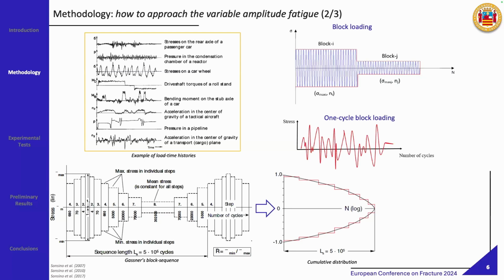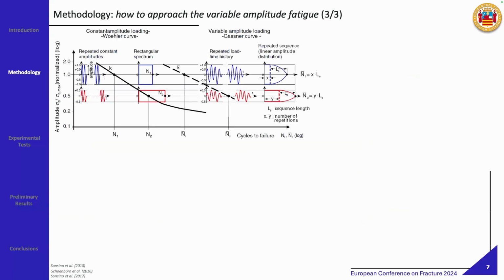And then we can obtain fatigue life curves for variable amplitude loadings, which are called Gassner curves in honor of Ernst Gassner. And they basically are generalized Wöhler curves. So we know that if we have constant amplitude loadings, we can obtain the Wöhler curve. And in case of constant amplitude loadings, the load distribution is a rectangular distribution.